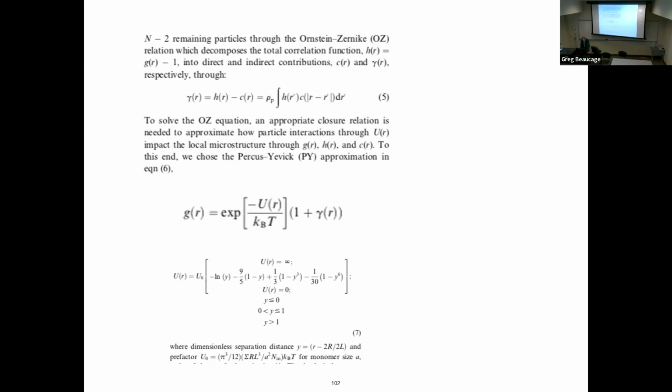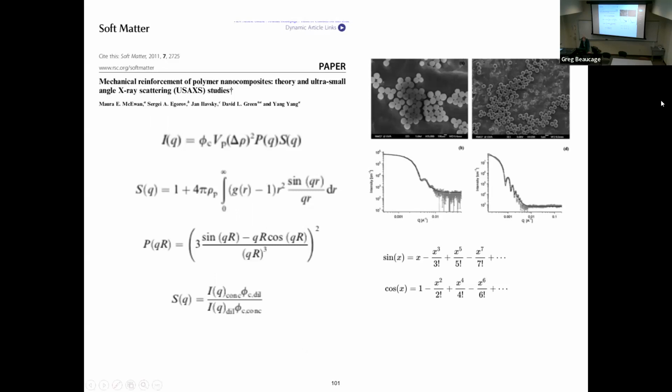So the way this works is in the scattering, you have the form factor and the structure factor. The form factor is what is the thing. In this case, it's colloidal spheres, so this is the sphere scattering function. If it's a polymer coil, there's no order to it. It's just the Debye function, the decay function, right? It's flat and then it goes down in a log-log plot.